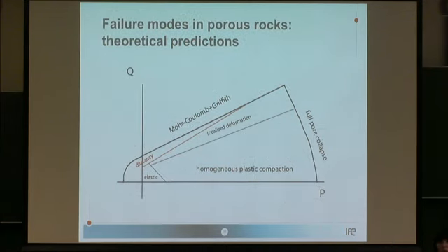And based on our small microscale models, we can also construct this failure envelope. This would reproduce the Mohr-Coulomb and Griffith criteria, and full pore collapse, which is captured by the model. We can also tell what would be the area of purely elastic or purely viscous deformation, where we can expect homogeneous plastic compaction, or where we can expect localization of deformation, areas of high strain rate, and even the compaction-dilation line. This is effective pressure P and this is shear stress Q. PQ are just notations that are most often used by experimentalists, so therefore they are used here.